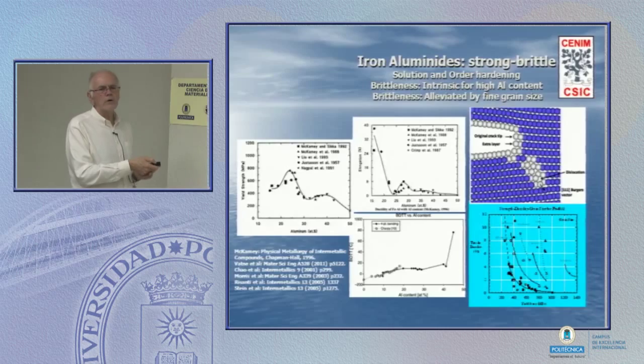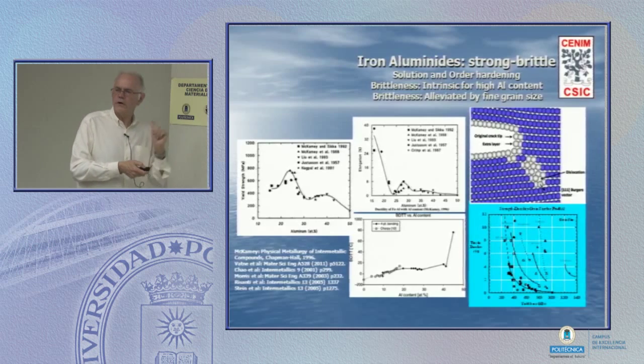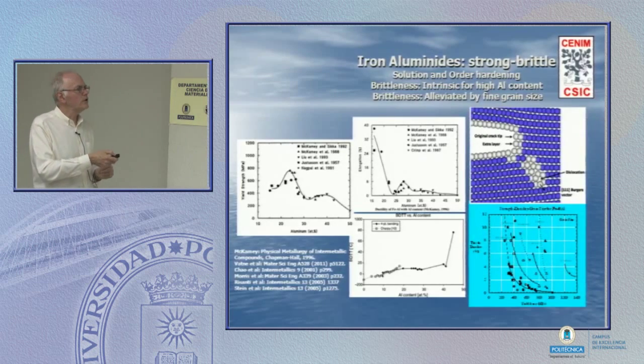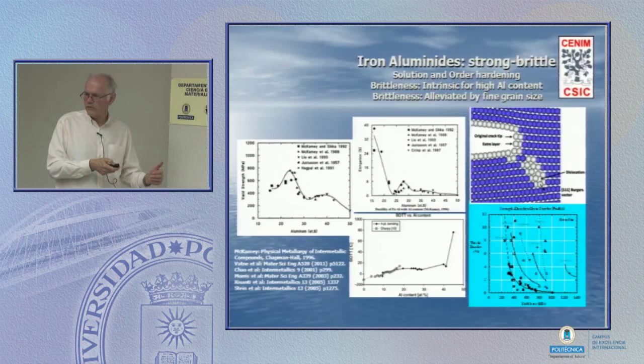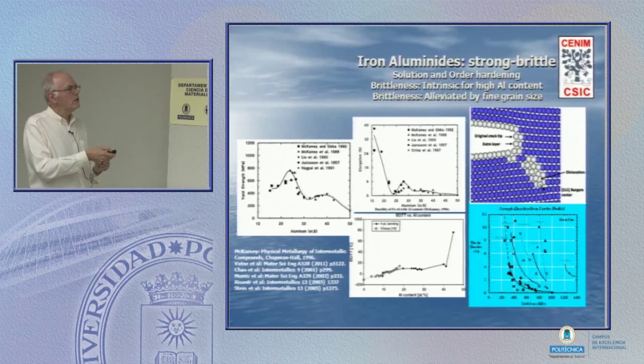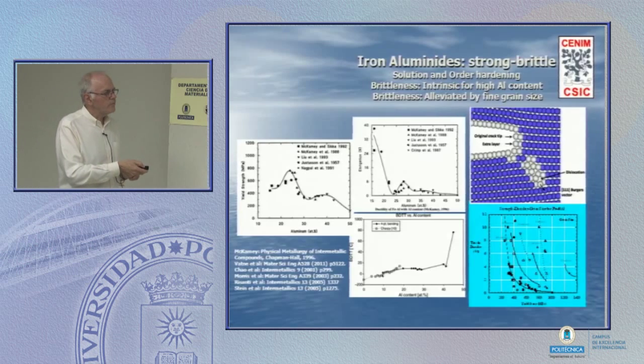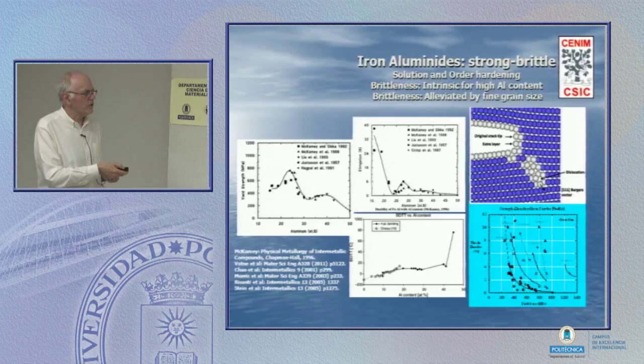And the reason for all of this, of course, is that we've made it difficult to nucleate the dislocation, difficult to move it away because of the pile-up stresses. And so the crack tip doesn't blunt. What do we need to do? As a metallurgist, we need to refine the microstructure.